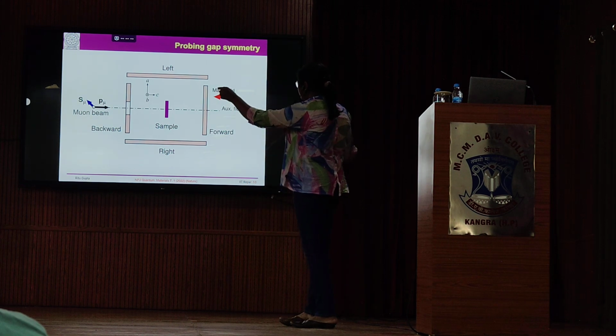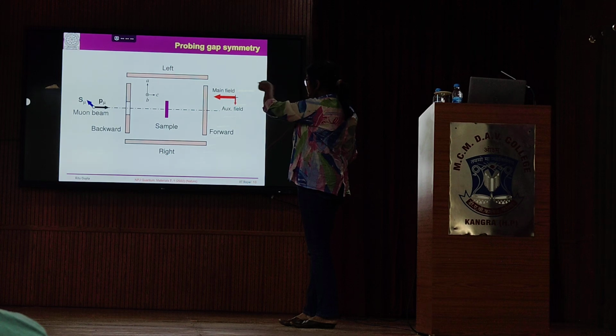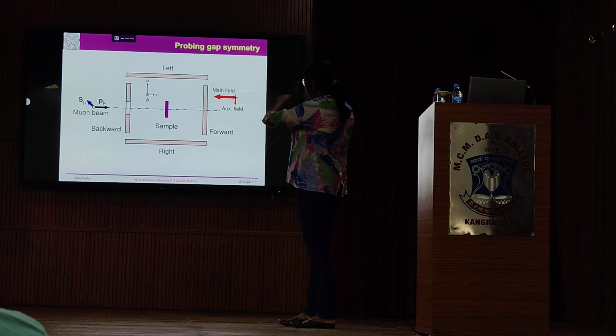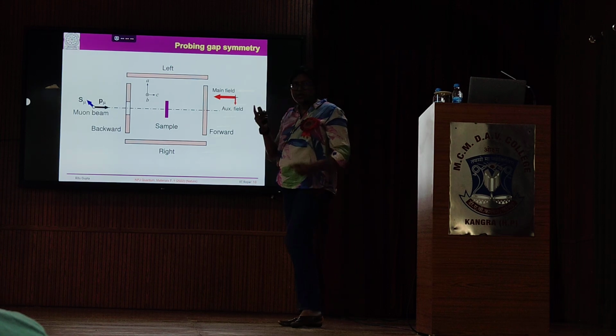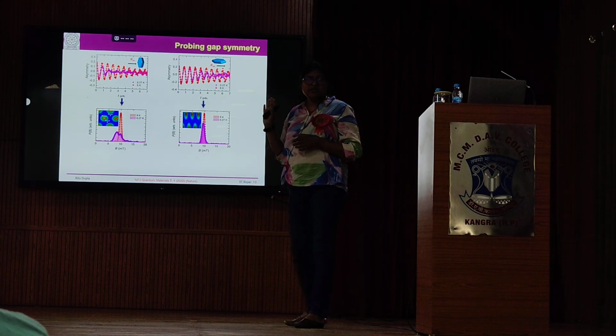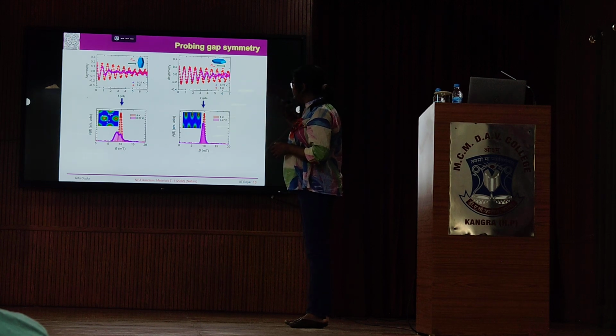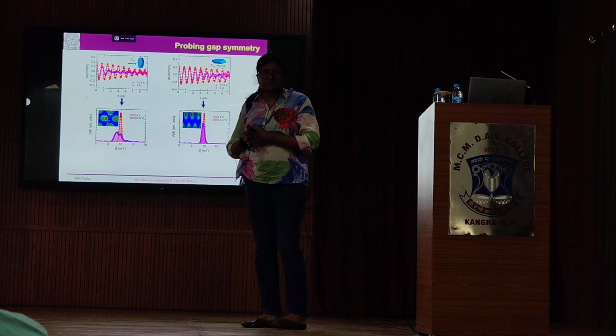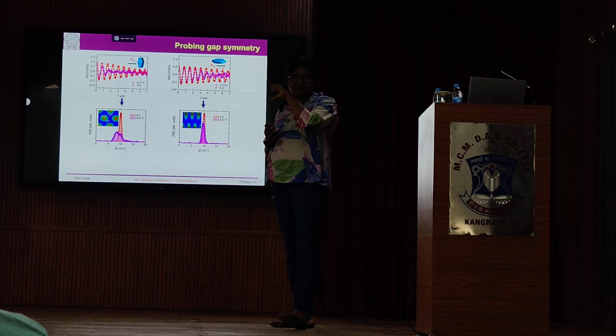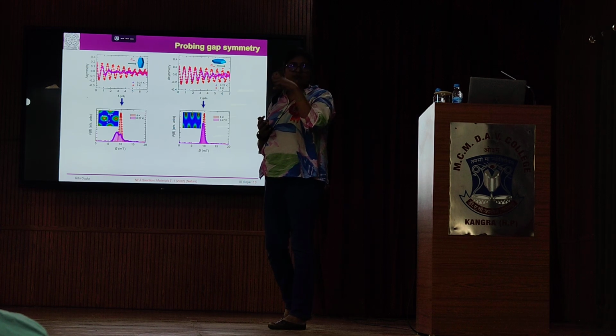So as I said, you see there is a muon with a spin coming there, and then you have 4 detectors, and in the middle is your sample. Okay, and you apply an external magnetic field, and then this muon spin will start precessing around that magnetic field, and you will get this type of spectra. So I already told you what kind of information you can get from this spectra. Just looking at the oscillation frequency, you can determine the magnetic field in that particular sample, and by looking at the damping of that signal, you can tell something about how the vortices are distributed inside the superconductor.